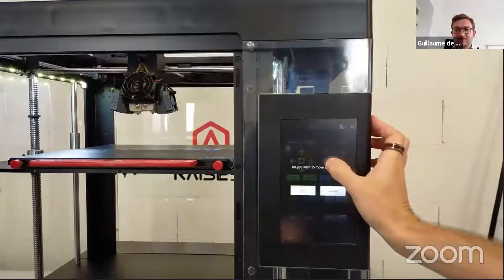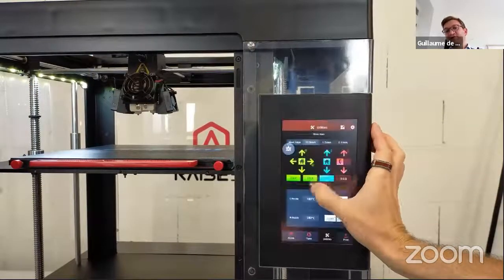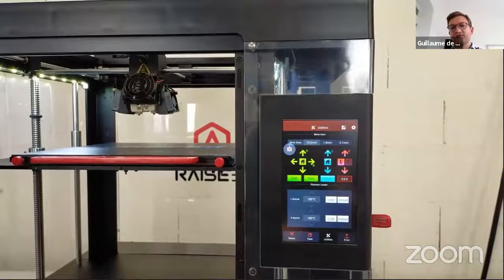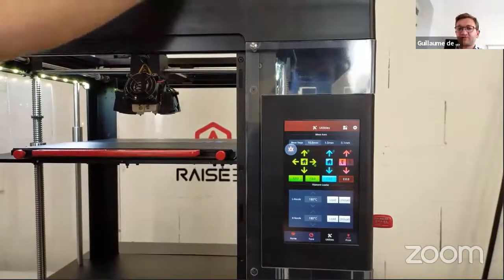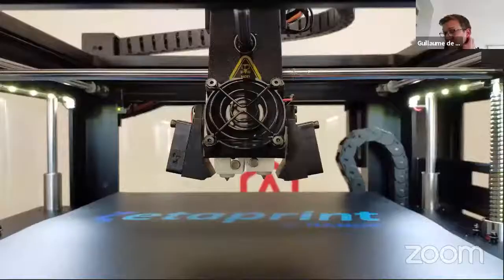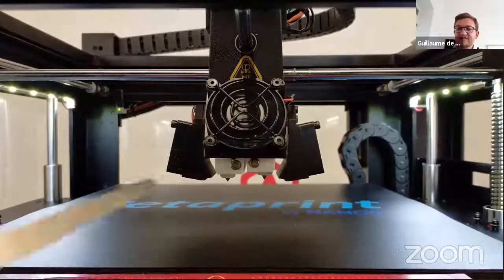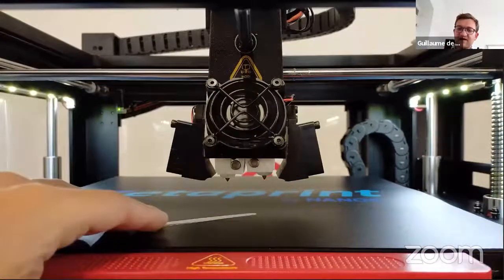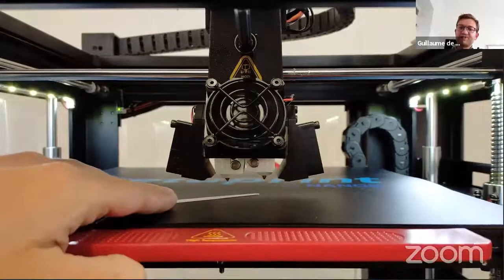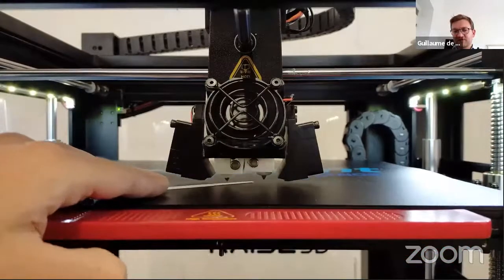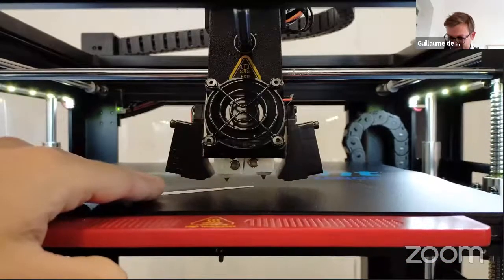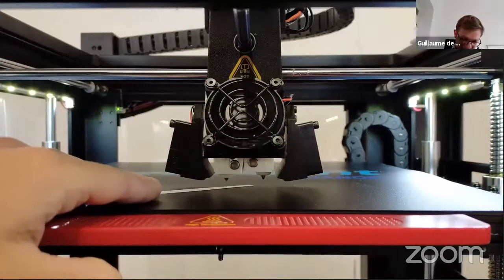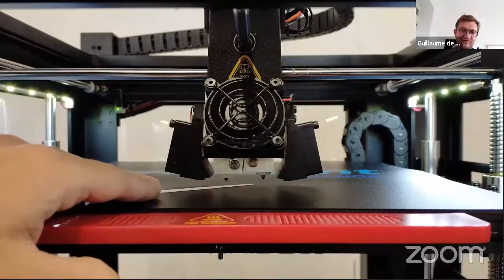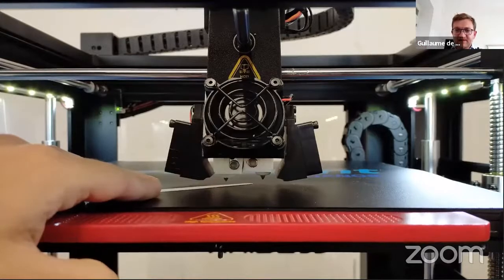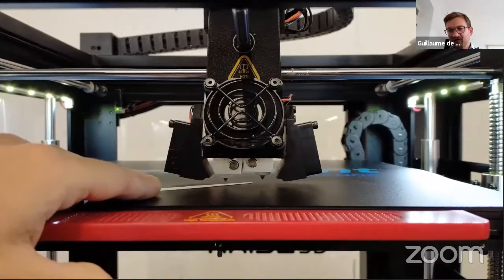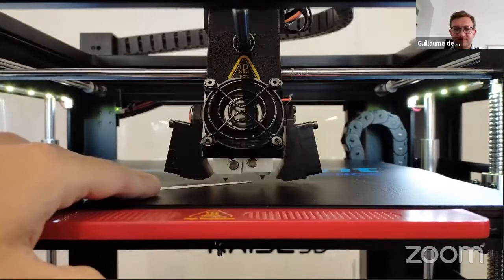Of course, we need to check the Z level, so that's done pretty simply by what we call homing the extruder. We're just going to tell the printer to go to 0, and we are going to check that there's still a small gap, a very small gap between the nozzle and the plate. That's what we aim at. The distance between the plate and the nozzle at 0 should be quite small, something like 100 micron, but not 0.